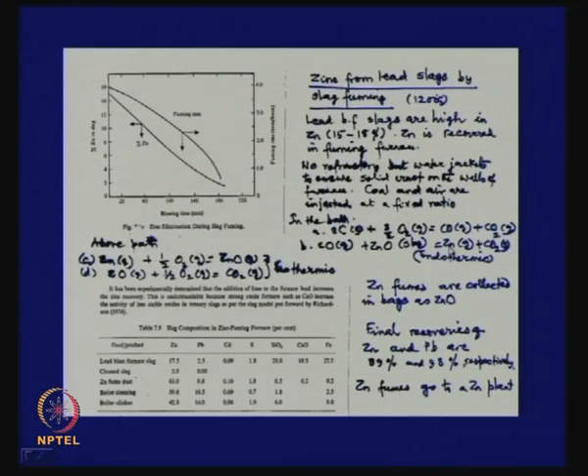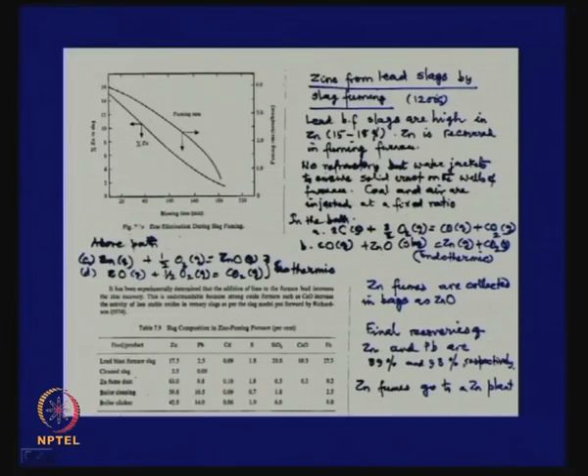So, it is a reduction reaction. There is zinc inside the slag as ZnO. Inside the slag phase itself, you inject carbon and oxygen, and these two react, coal rather, carbon as coal, these two react, gasify coal, the CO formed reduces zinc oxide, zinc vapors come out. This is an endothermic reaction, because all oxide reduction processes by CO are endothermic.